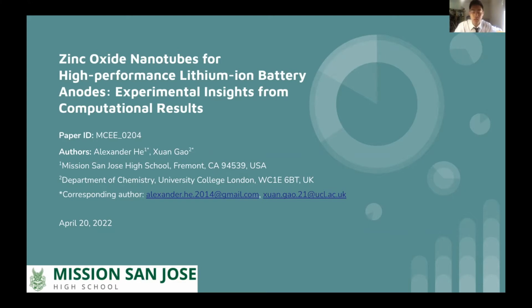So in this study, zinc oxide nanotubes were simulated and calculated to get their bandgap and density of states to predict their performance as anode materials for lithium-ion batteries. With the insight of reducing the bandgap by nanomaterialization to improve performance, zinc oxide nanotubes were fabricated with hydrothermal reactions. We tested performance after 100 cycles and confirmed that the nanotubes are better than bulk zinc oxide in many regards, including electron conductivity, bandgap, Coulomb efficiency, cyclic stability.